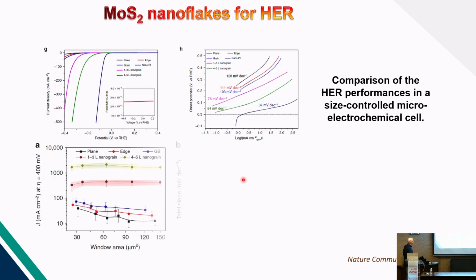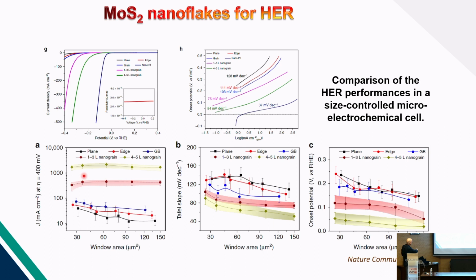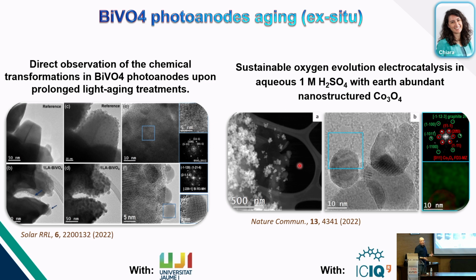And then the electrocatalysis is giving you that in the case of the multiple grain boundaries, you have the highest intensity, and the basal plane is really not working at all. But also here, the Tafel slope or the onset potential are the lowest for these nanograins, which are the ones that are giving a better catalysis. But at the end, in order to understand that, it's good to simulate, but in order to simulate, you need to know the structure. And the only way to get the structure is getting these nice pictures in the electron microscopy, and then, of course, understand the material and create the models.